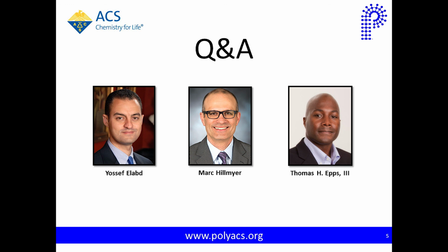And so there's work from the Lodge group and others where they've looked at not just taking that traditional PEO-based material, but taking that, again, putting in, whether it's glymes, other types of materials, low molecular weight homopolymer, putting in ionic liquids, and using that to really drive up the room temperature conductivity, and I can typically do that by several orders of magnitude.